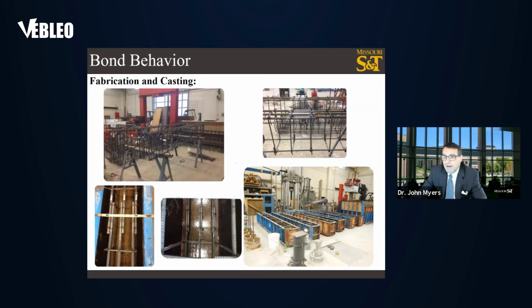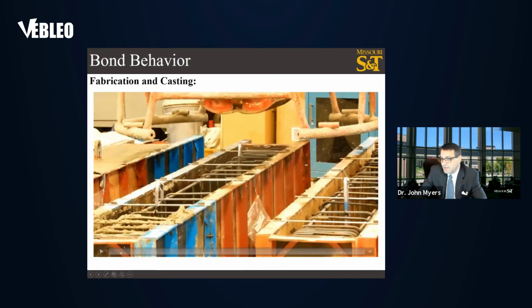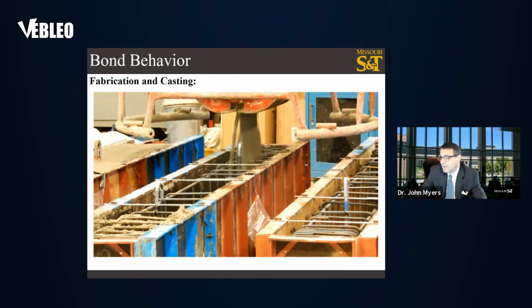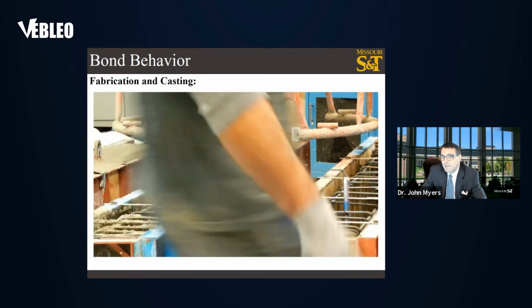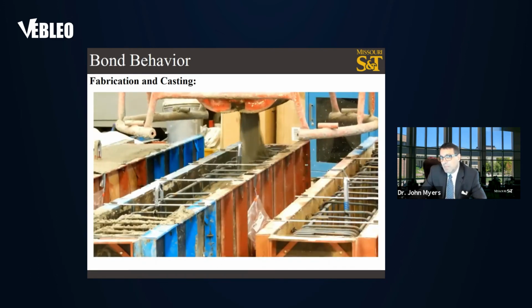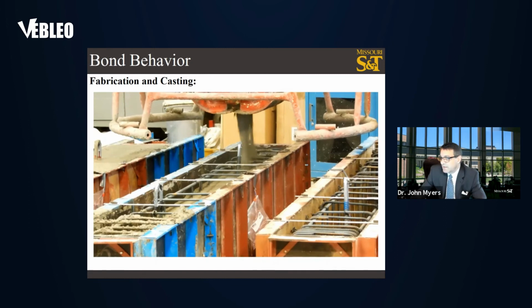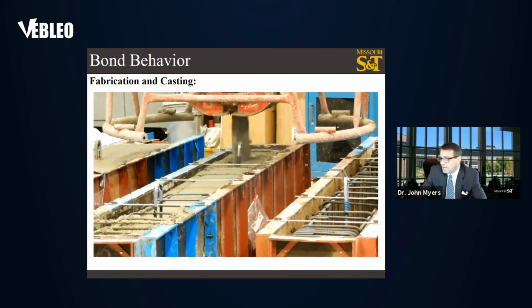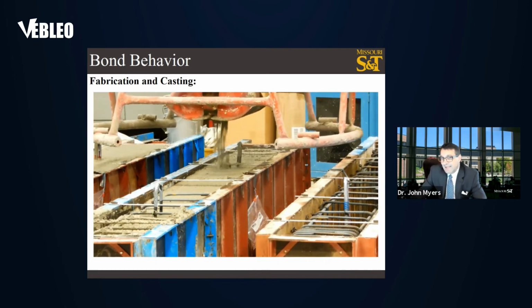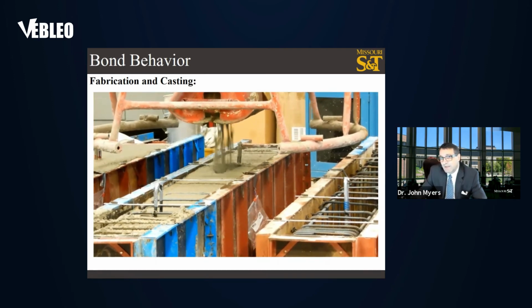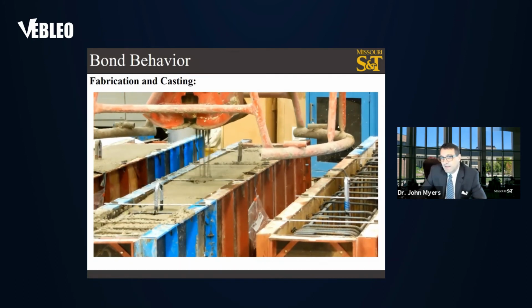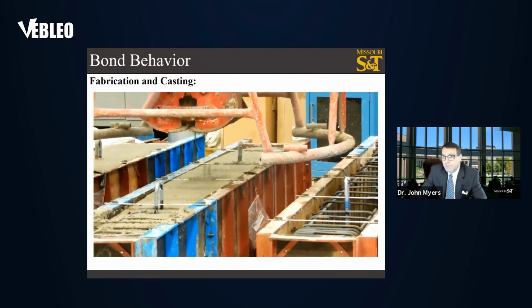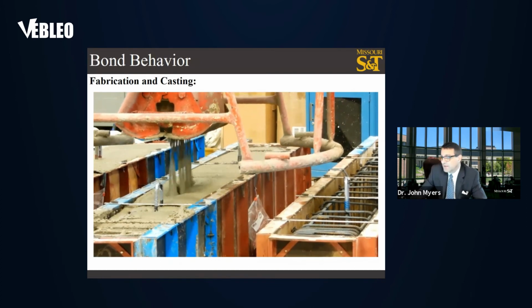Here you can see the fabrication of the cages as well as the production of it. Just going to show you in this very brief video here the flowability of the high volume self-consolidating concrete. So you can see no labor is required to vibrate the concrete, and there is no segregation in the mix that we developed, meaning the aggregates are evenly distributed between the bottom and the top of the concrete element.